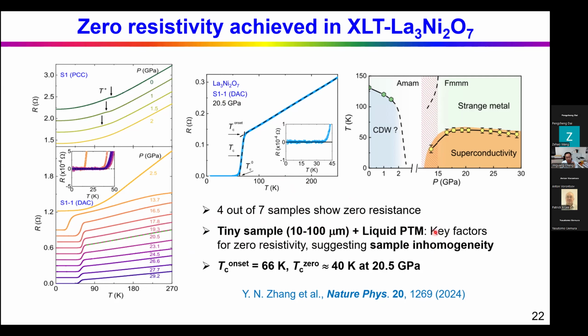So this indicates that the sample is not very homogeneous. So you have to pick a very small sample, and the sample may be homogeneous in the small region. And the TC onset transition is quite sharp. The onset is about 66 Kelvin, and the zero resistive temperature can reach 40 Kelvin at 20 GPa. So this is, I think, the first signature of superconductivity where zero resistivity is achieved. But in this paper, no Meissner effect was reported.